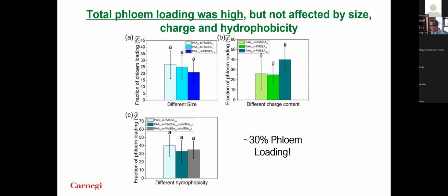So one of the things that we hypothesized was that all of those factors, charge, size, hydrophobicity, would affect phloem loading. And then it turned out that it didn't affect phloem loading at all. For all the particles we put on, approximately 30% of what we put onto those leaves ended up in the phloem, regardless of size or charge or hydrophobicity. So that was actually a little disappointing. We thought that we could keep things in the leaves or put them in the phloem and move them to roots, and we thought we could do that. But it turned out that we couldn't affect phloem loading with any of those properties.